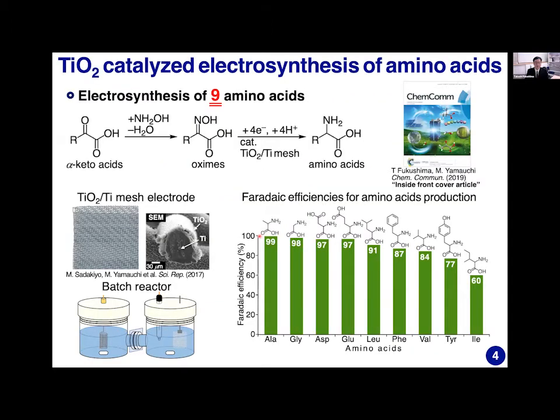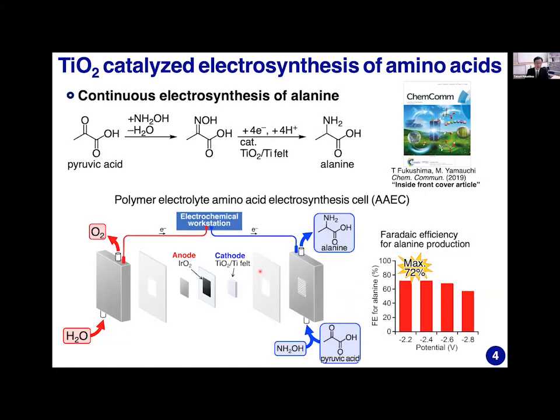Recently, we have reported that titanium oxide grown on titanium mesh electrode catalyzes electrochemical conversion of alpha-keto acid into the corresponding amino acid in the presence of hydroxylamine with remarkably high Faraday efficiency of 60 to 99%. Furthermore, we also tried continuous electrosynthesis of alanine using the flow-type electrochemical reactor shown here. And we achieved a maximum 72% Faraday efficiency for alanine production.